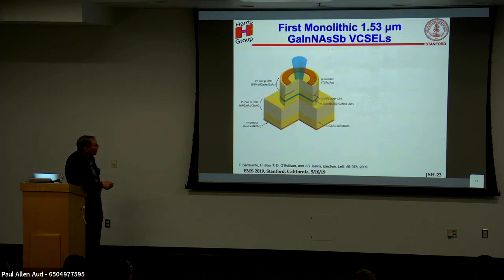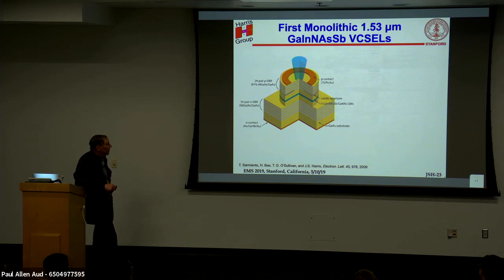So then, making good edge emitters, we said, well, the whole idea was really to make VCSELs. You could do this all monolithically because you could grow on a gallium arsenide substrate. You could grow aluminum gallium arsenide DBRs, have a quantum well, and use the oxidation of aluminum arsenide to create an aperture that gave you electron carrier confinement, which improves the threshold, but allowed a little larger area so the heat sinking was better. So you got both optical and electrical confinement. Those are all just sort of good luck. It just happens with that material system.